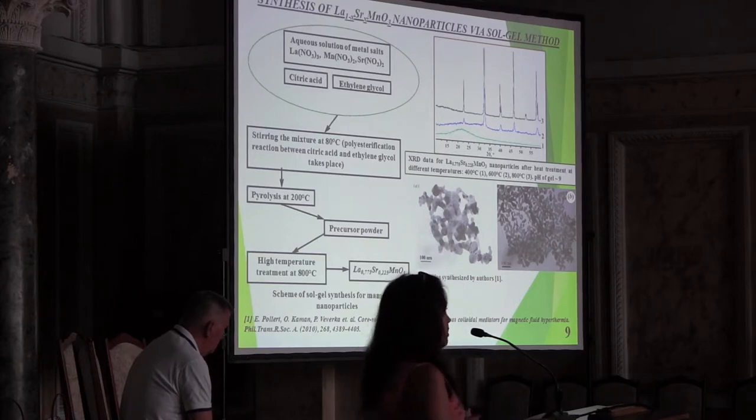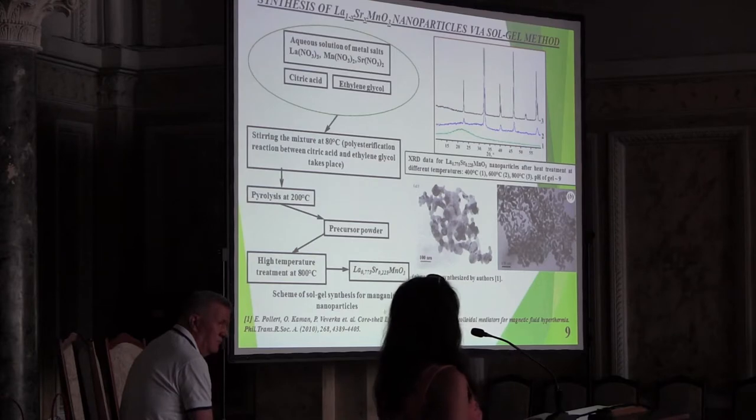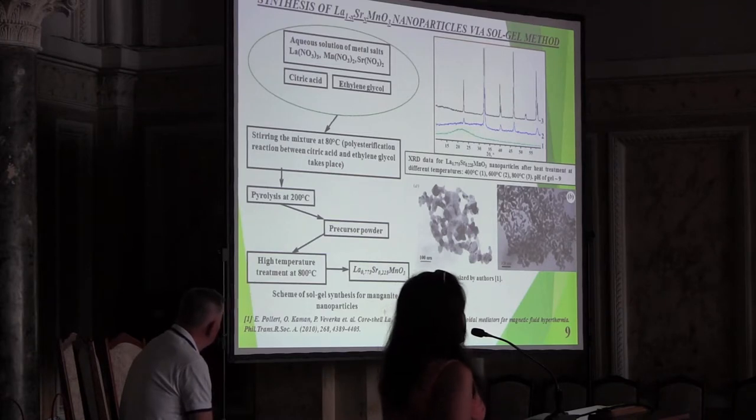I would like to tell you that previously, in 2010 in the Czech Republic, such nanoparticles were synthesized via the sol-gel method. However, such nanoparticles were large and strongly agglomerated, and the scientists suggested doing mechanical grinding. They obtained nanoparticles with different shapes and a wide size distribution from 20 to 120 nanometers.